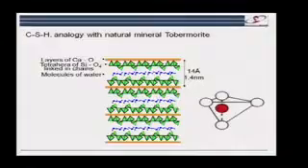And this is where we can see about the chains and about sharing. Depending on how many other silicates these are linked to, you see in these chains, each of these tetrahedra is linked to 2 others. So these would all be Q2 groups. And then finally, we see that between these layers, we've got water molecules. So those are the 3 basic elements of tobermorite structure and also of CSH structure. It's a sheet structure of calcium oxide sheets with silicate chains on it.